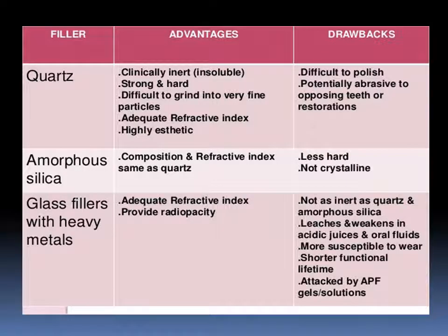So this is a summary of the three fillers we discussed. Quartz: the advantages are that it is inert, strong and hard, but difficult to grind into very fine particles. It has good aesthetics and an adequate refractive index. However, the drawback is that it is difficult to polish and potentially abrasive to the opposing teeth or restorations. In case of amorphous silica, it has the same composition and refractive index as quartz. However, a drawback is that it is less hard and not crystalline enough.